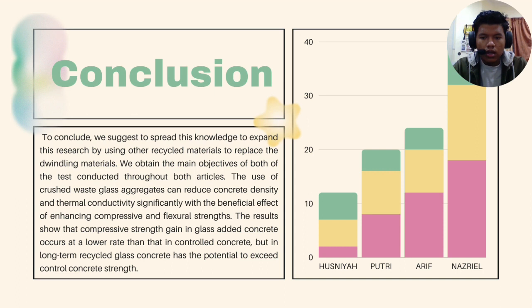The results show that compressive strength gain in glass added concrete occurs at a lower rate than the controlled concrete. But in the long term, recycled glass concrete has the potential to exceed controlled concrete strength.